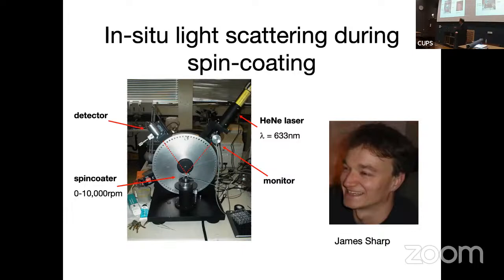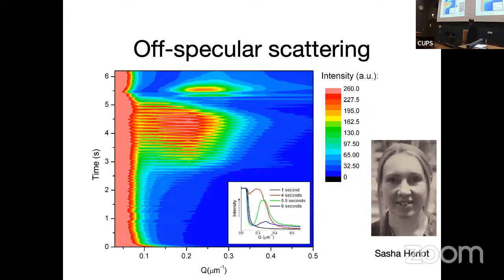And then you get a very, very uniform, smooth film. So this is a very, very common technique in any kind of thin film experimentation with polymers. So this system is just a little device that allows you to do that. But while it's doing it, you bounce a laser off it. So you just do light scattering to see what's happening. And so my postdoc, Sasha Heriot, at the time, worked out you could use this to see what's going on